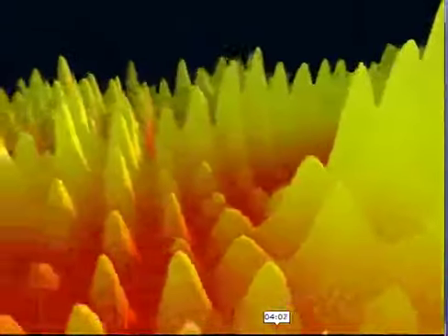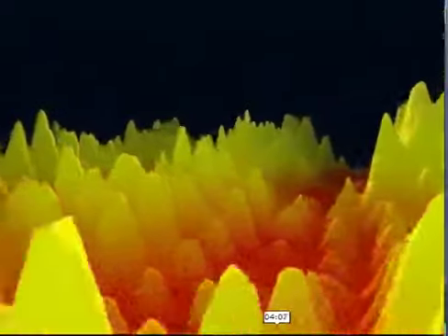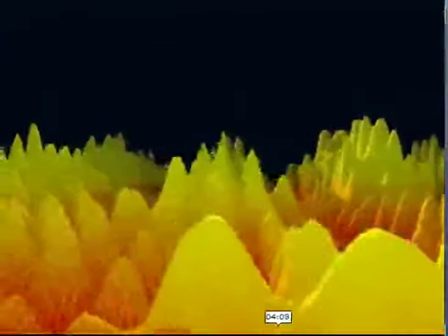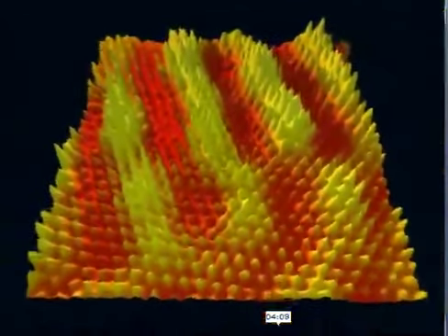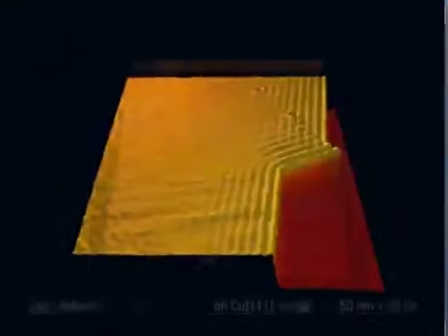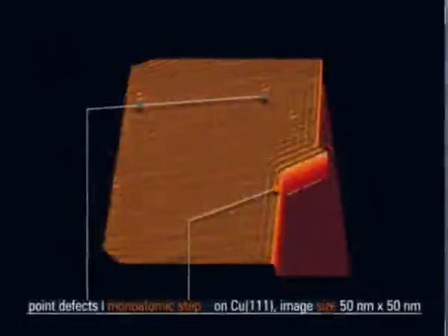Varying background. Typical modulation lengths are of the order of 1 nanometer, 5 times as long as atomic distances, and they are due to variations of the electron density within a surface. The tunnel current depends also on the electron density of the sample. Therefore, investigations of the electronic properties are possible. We study how the electron density varies due to electron scattering processes. We observe a wave-like modulation pattern of the electron density. Its characteristics are described by the laws of quantum physics.